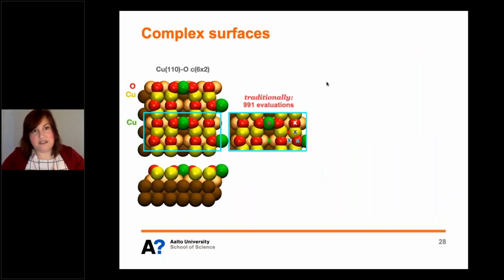What Diego also did is consider a much more complex surface. Here's the C6x2 reconstruction, where you have this green atom coming in. It's another copper that distorts the added rows. And now you have to take a much larger chunk of the surface that repeats itself. And this was a tough problem. So Diego tried to estimate 7 different potential adsorption sites, and he relaxed the molecule above them. And this was about 1,000 DFT evaluations.